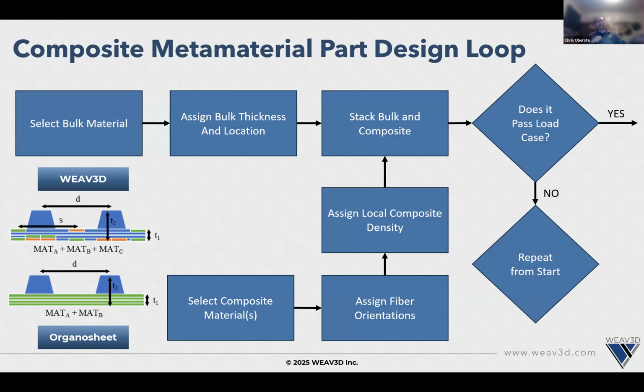The problem is, because you have all these different variables that influence each other, you have to go back to the beginning to redesign this part. You can't just tweak one or two variables very easily because they're very closely coupled. So changing the total amount of bulk thickness in one area also changes the local density of the fibers for the composite portion of the structure. So this is what we talk about when we talk about metamaterials: there's a complicated relationship between the material properties and the structure that those materials are applied to and how they are distributed within the geometry that you're producing.